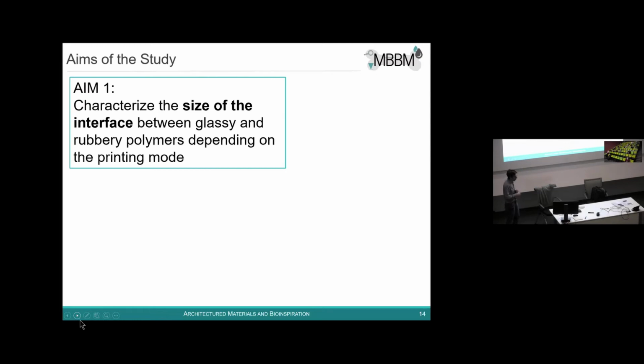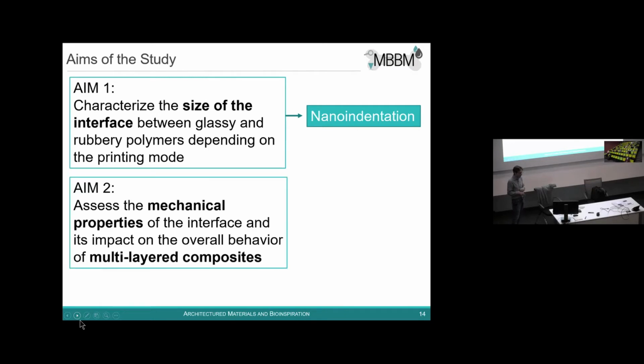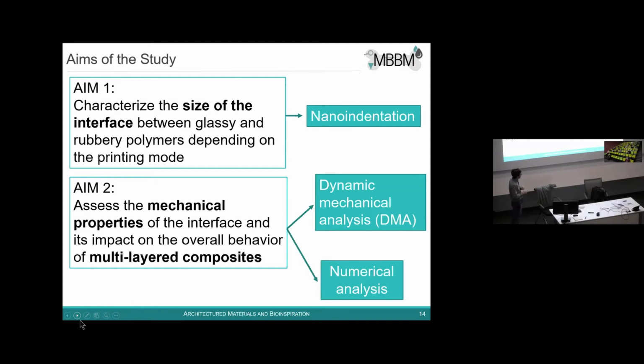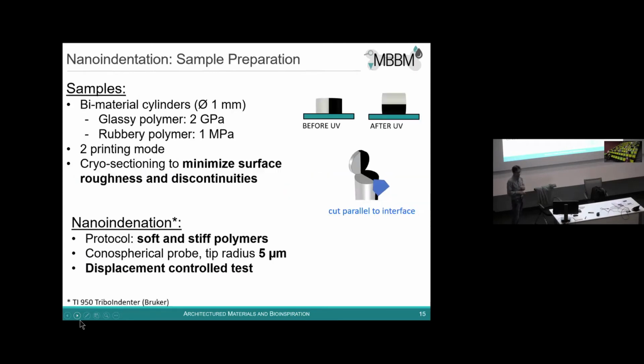So the two aims of this research are, first, to characterize the size of the interface between these glassy and rubbery polymers. For that, since we have micrometer length scale droplets, we have to use a technique which allows this resolution, and so we chose nano-indentation. Then we want to assess the mechanical behavior of the interface and the impact of having an interface which is not ideal, so not a zero thickness interface, on the behavior of multi-layer composites, simple multi-layer composites. And for that, we use dynamic mechanical analysis and some numerical modeling.